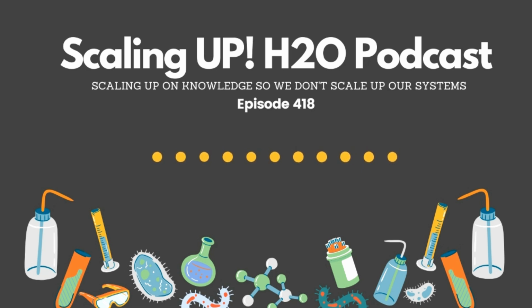From a results point of view, I think dosage is very important. The tendency of a lot of people is to underfeed these materials, and I don't think you can necessarily do that. I think at a minimum, you need 5 to 10 ppm active of these types of materials. You can definitely see a correlation between dosage and corrosion rates. Where we've seen some applications less than 5 ppm active, we've seen corrosion rates that have not been off the charts, but been 4 or 5 mils per year. So it's critical to titrate, if you will, the corrosion inhibitor to the rate that you're expecting.